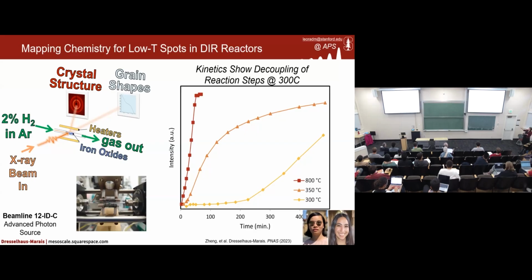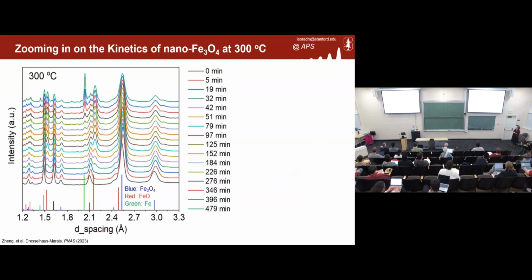and we can see that at the highest temperature, it's a fast reaction that we generate all the iron we're going to, almost instantaneously, whereas in the other temperatures, we start to see that it's slow until we actually see a separation of the kinetic steps. So with that, we were able to, at the very lowest temperature, separate these out into a more streamlined approach, and we were able to observe how each of the phases grow in as a function of reaction time. So as we did that, we observed the formation of wüstite, even at 300 Celsius.